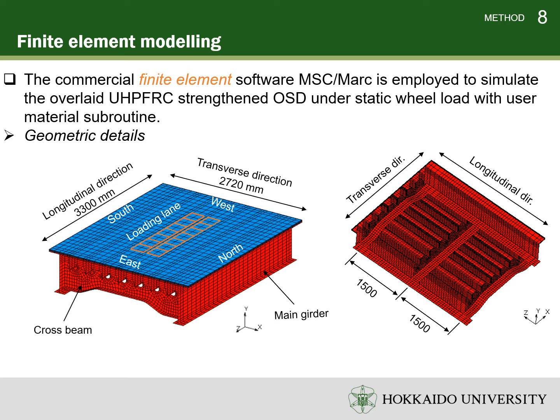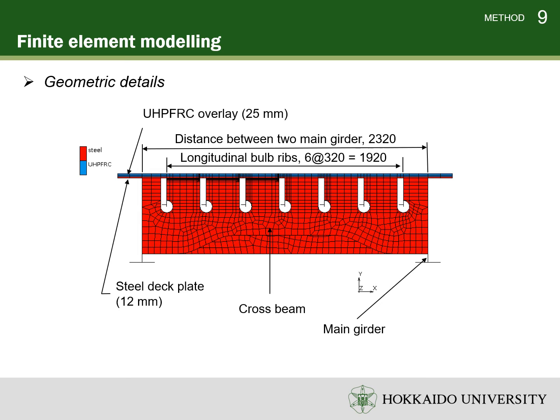Geometric detail of composite deck. These figures show a steel deck with a span of 3,300 mm and 2,720 mm along the longitudinal and transverse directions. The strengthened bridge deck is composed of the UHPFRC overlay, the steel deck plates, the main girders, the cross beams, and longitudinal bulb ribs. Along the transverse direction, the steel deck is supported by three cross beams with a spacing of 1,500 mm. Along the longitudinal direction, the steel deck is supported by two main girders and seven bulb ribs with a spacing of 320 mm. The steel deck plate with a thickness of 12 mm is overlaid by a layer of UHPFRC with a thickness of 25 mm.